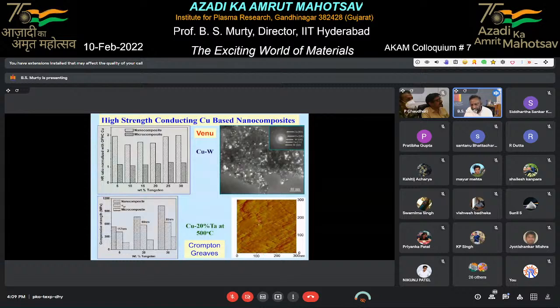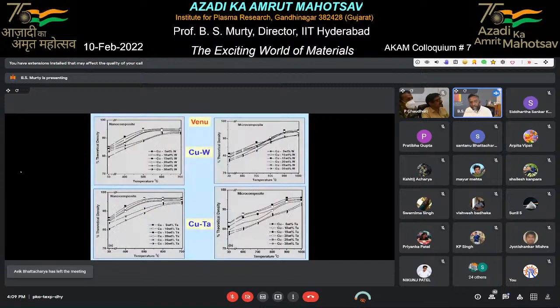The grain size is 30 nanometers. Please note that these are all completely 100% sintered pellets, and you still retain such a small grain size. That gives you 3 times the strength of what is called normal oxygen-free high conductivity copper. And these are all possible. We can also demonstrate that these alloys, which we call nano composites, can be sintered at a much lower temperature when compared to a normal material.